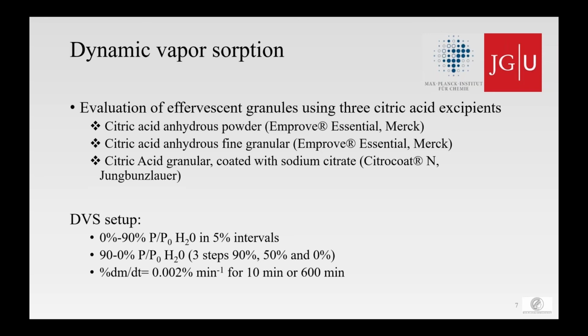For our experimental setup, we chose to start at 0% relative humidity and go up to 90% relative humidity in 5% intervals. And this is done at 25 degrees. And since we want to measure the resistance toward humidity and our product reacts when it's exposed to high humidity, it will be irreversibly destroyed once it takes up too much moisture. So we didn't investigate the desorption process too closely. So we had 3 steps of desorption. Just from 90%, we went to 50% relative humidity and then to 0% relative humidity.